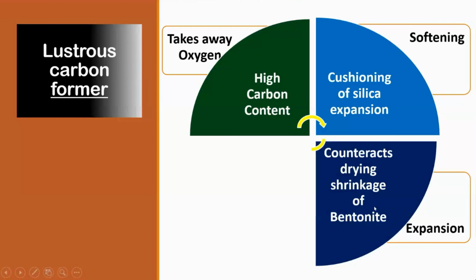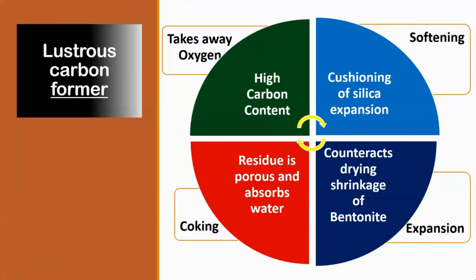Shrinkage is because bentonite is losing the combined water, and what has swollen during the molding process is going to shrink back to its original state because of the loss of moisture in the combined. All the hydroxyl ions are going to be lost. So then that shrinkage space is taken by the expansion of this coke. The only negative aspect of this lustrous carbon is the coking. The coke that is produced because of this expansion is a residue which is porous, and then it is a dead matter. It is going to absorb a lot of water by itself and then rob the bentonite of the water that is needed for development of bond.